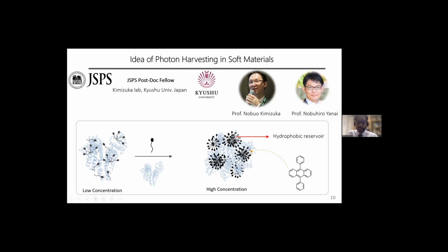And because of its thick fiber network of protein at high concentration, it can prevent oxygen inflow into the chromophore region. So I can solubilize the chromophore in the hydrophobic domains of the surfactant, and the protein can act as an oxygen barrier.